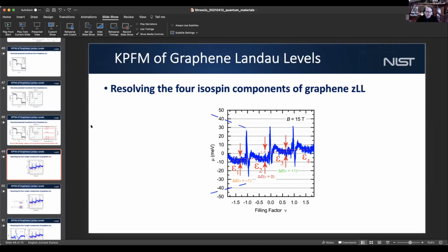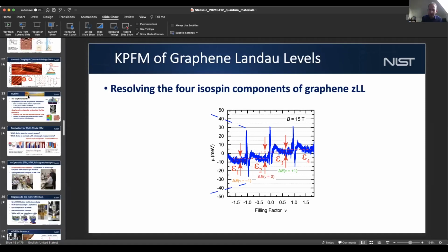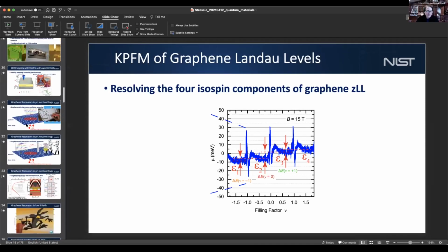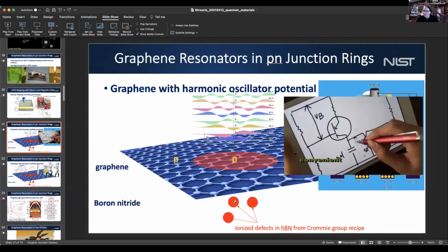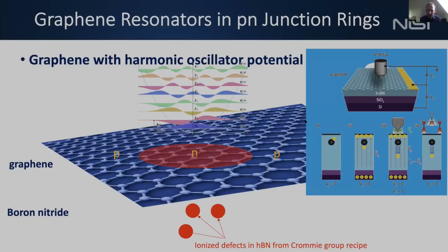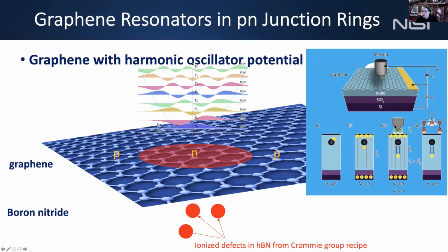You achieve this potential by ion doping in the boron nitride, if I understand correctly. It's natively doped. There are native defects in the boron nitride. Then we park the tip above the graphene and apply about 5 volts, and that ionizes these defects. So you create a field above the graphene that ionizes the defects, and if you have the backgate field on, it draws the charge away, and when you take the backgate away, that charge stays there.